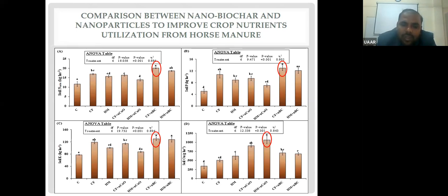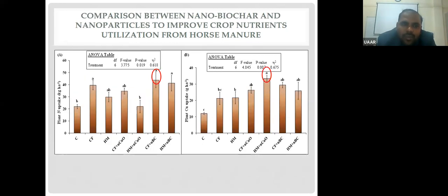However, if you look at the copper content, because copper is present in the copper oxide nanoparticle, the copper content in the soil was improved when horse manure was applied with nanoparticle of copper oxide. Next, if you look at the plant nitrogen uptake, it was also higher when chemical fertilizer was mixed with NANO-BIOCHAR of horse manure. Similarly, copper uptake was improved where there was more copper in the soil with horse manure and nanoparticles of copper oxide.